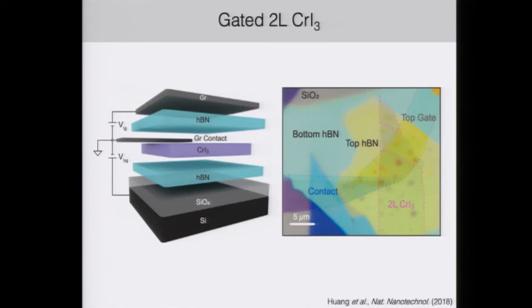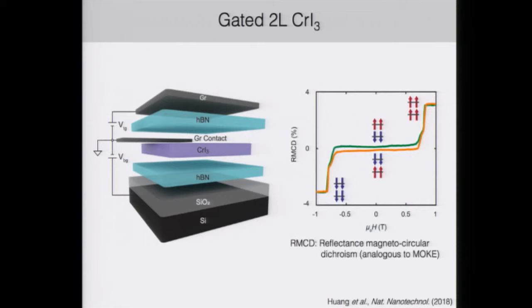In order to do so, we fabricated these gated bilayer chromium iodide devices, where we have a bilayer chromium iodide flake and a graphite contact, 2 hexagonal boron nitride layers, which both protect the chromium iodide flake and also serve as dielectric layers, as well as a graphite top gate and a silicon back gate. Here's an optical microscope image of the device, and here's the bilayer chromium iodide flake. In the absence of applying any gate voltages, we're able to reproduce the signals that we've seen previously with MOKE.